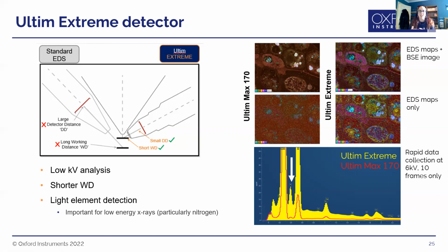So it changes depending on the microscope, but it's around 5 millimeters, and it can be pushed a bit further, which means you get much better image resolution as well as much better signal from your sample. And because we're that much closer, we're capturing much more of the X-rays that are emitted. Now, for life science samples, this means that we get a lot more signal, and we've got in particular nitrogen.